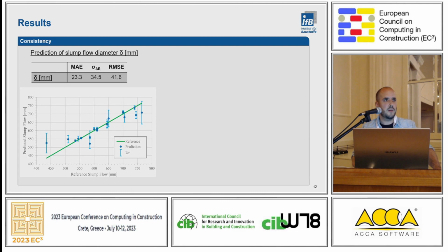And in the graph below, we can see the reference curve, which is the green line, and we can see the distribution of data samples around the line. And we can see that especially at the boundary cases of the parameter range, so in the upper and lower boundary, we have the largest error range, which we think comes from the long tail problem, that we have a less dense coverage of these parameters in the training data set.